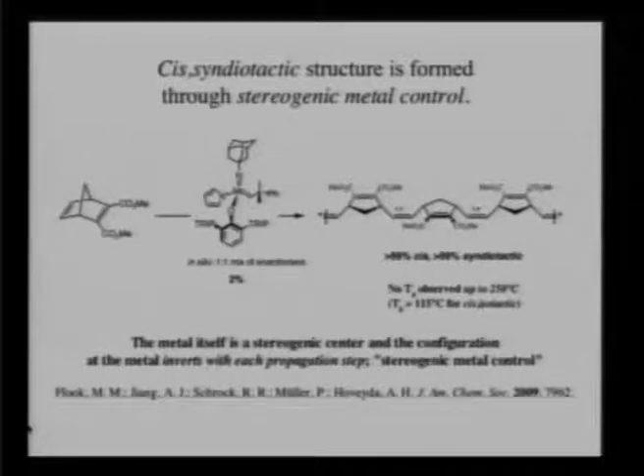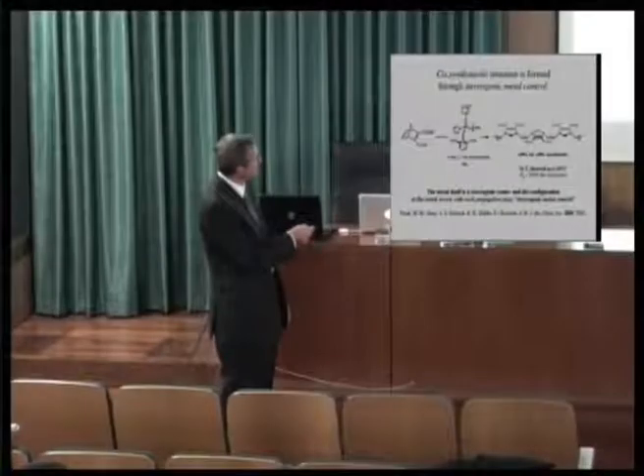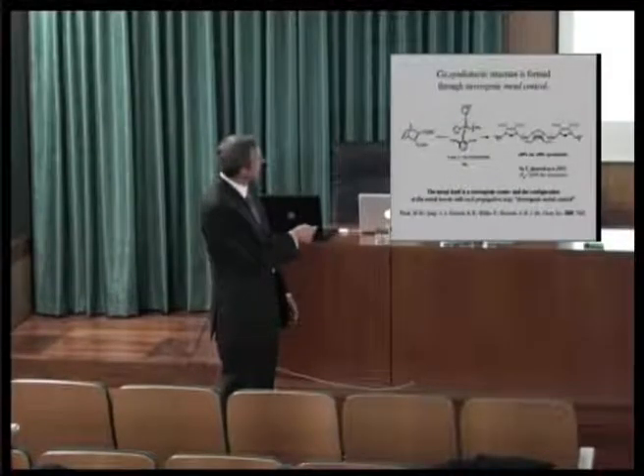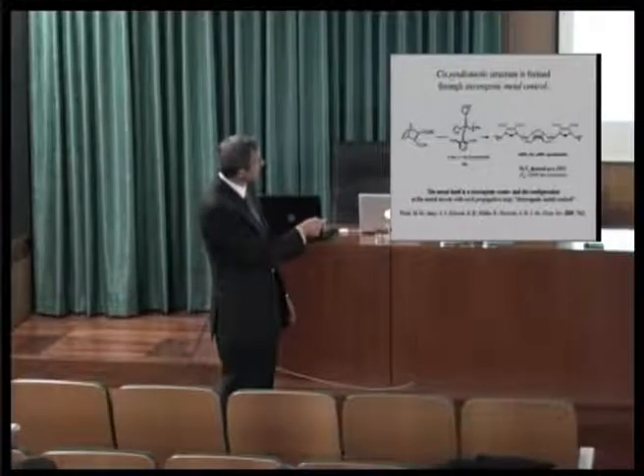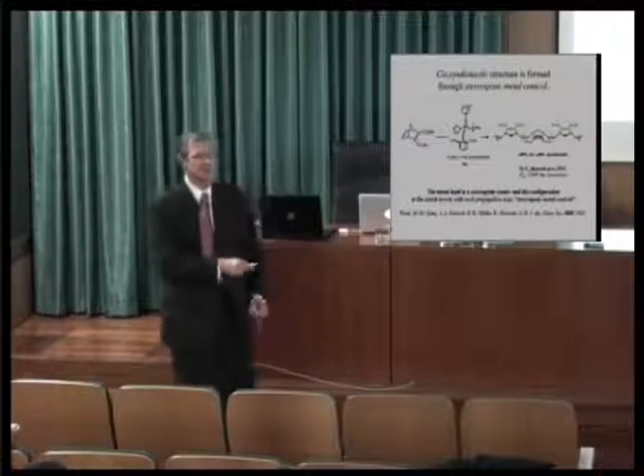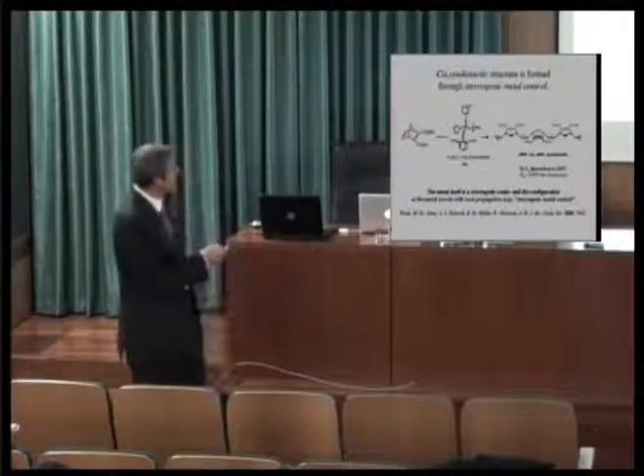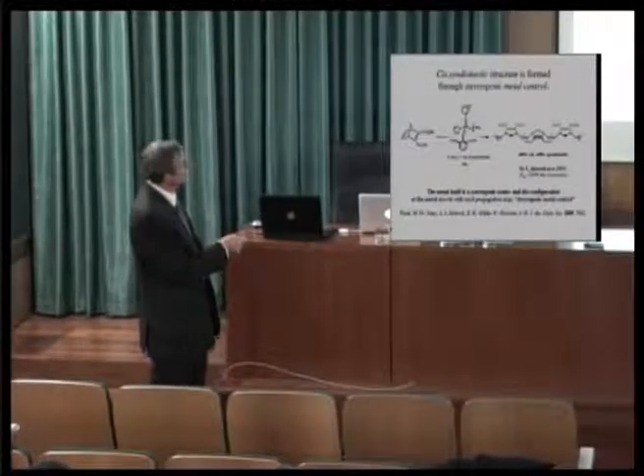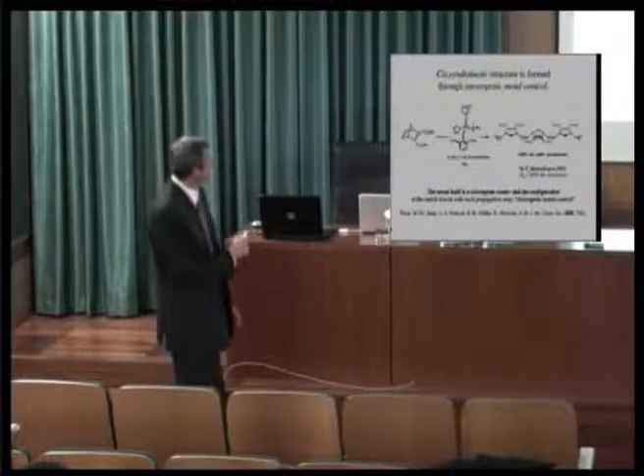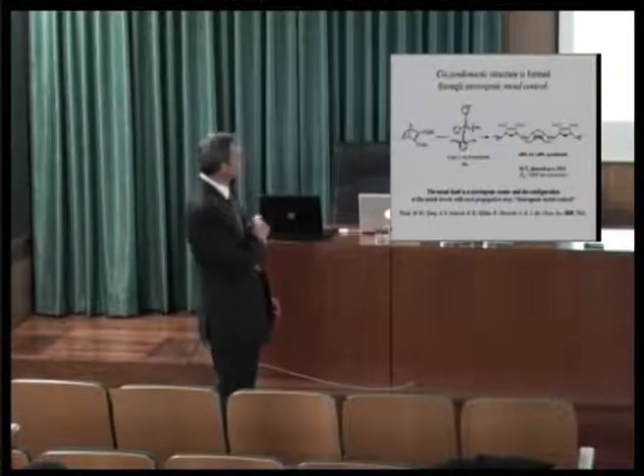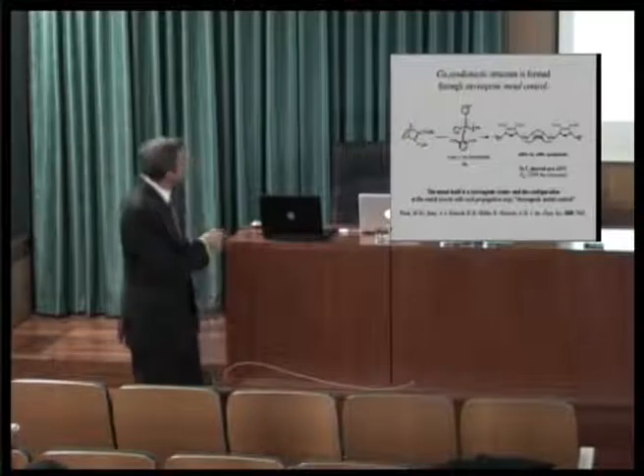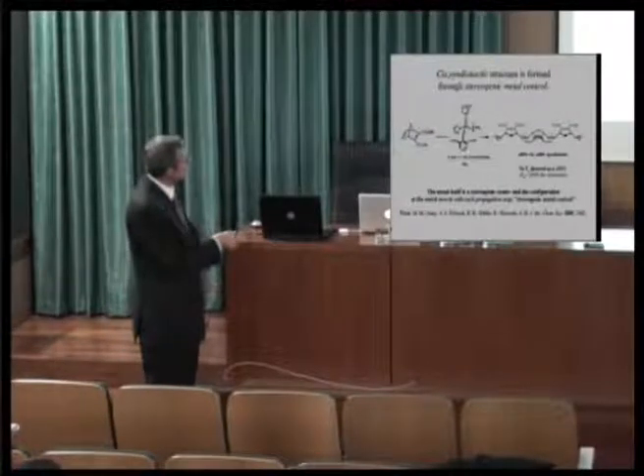They have different properties. The glass transition temperature for this one is 115 degrees. We can't observe a glass transition temperature for this one up to 250 degrees. So very different polymers based only upon which direction these rings point. So we reported this back in 2009 also. We call this a stereogenic metal control.